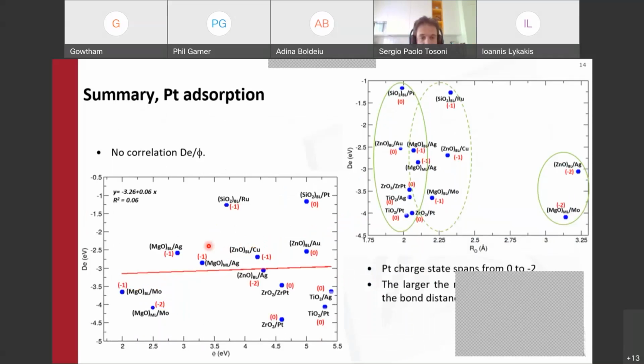If we try to play the same game with platinum, well, nothing works. The correlation is really not existing. Platinum doesn't care about the work function of the substrate because it forms mostly covalent bonds. So it doesn't matter if you have shallow donor states or deep acceptor states. It is more a matter of how much the film adapts to the adsorption of platinum to form strong covalent bonds.